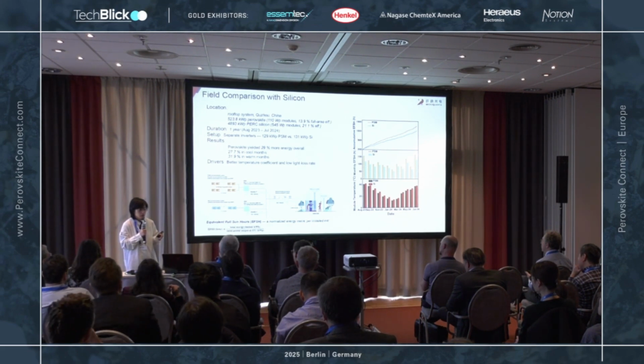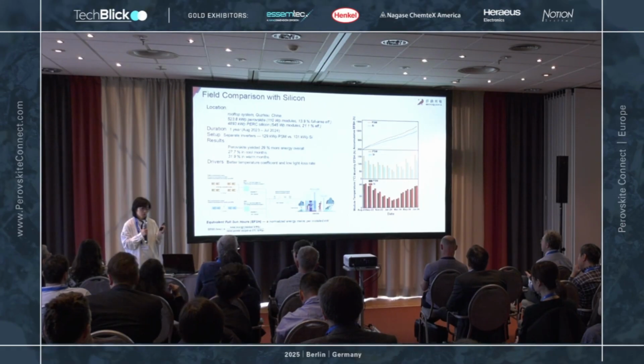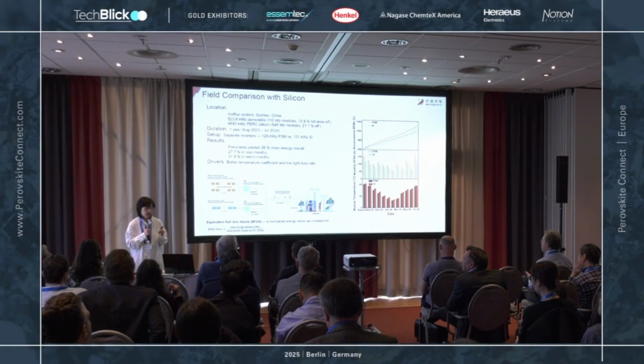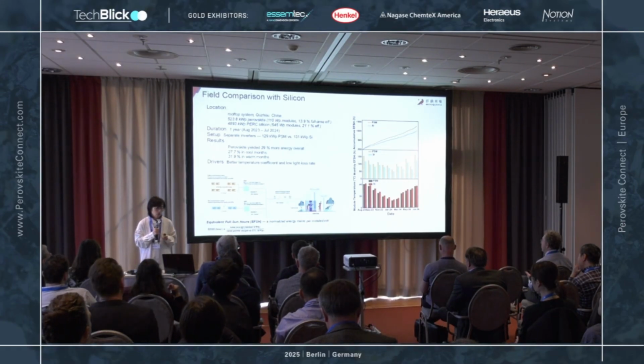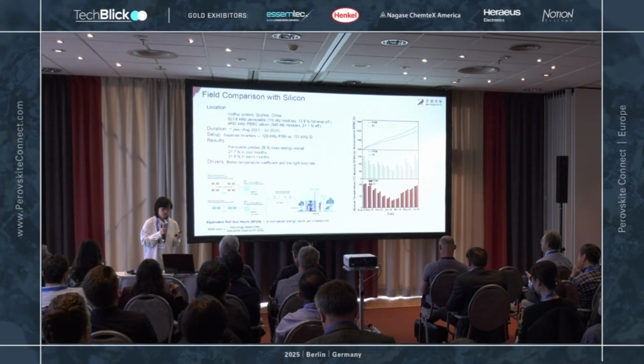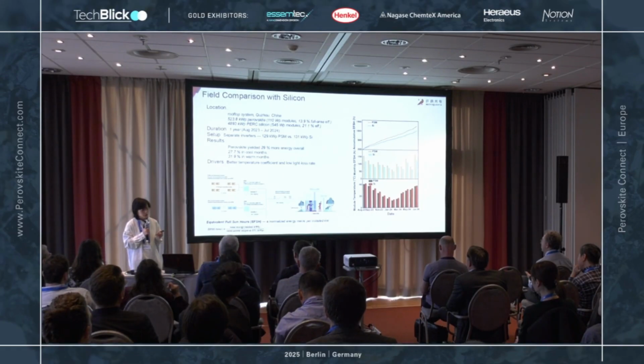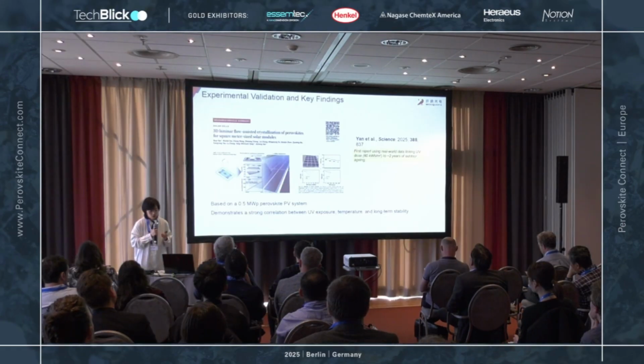What we found here is perovskite actually generates 30% more energy than silicon, even at lower efficiency. It means 27% more in cool months and 32% more in warmer months. And the driving factor behind this is that perovskite has a really great temperature coefficient and low light response.